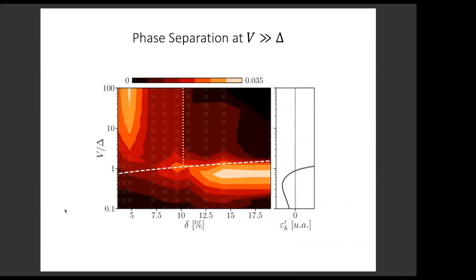So I stayed much away from this large V limit, when the interaction V is much bigger than the band gap. Then something else happens. Here, the color represents the superfluid stiffness. And you see that at higher doping, at large V, the stiffness dropped to 0. So we believe, and also in the exact diagonalization, we see that there are many degenerate ground states. So we interpret that as phase separation.